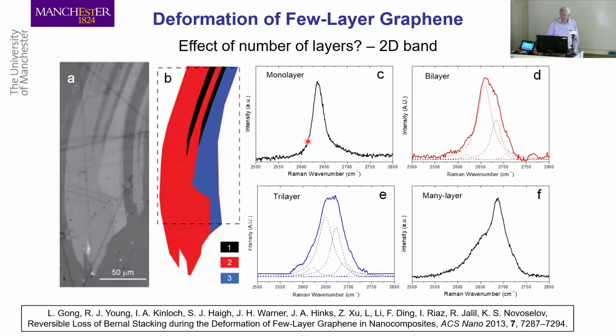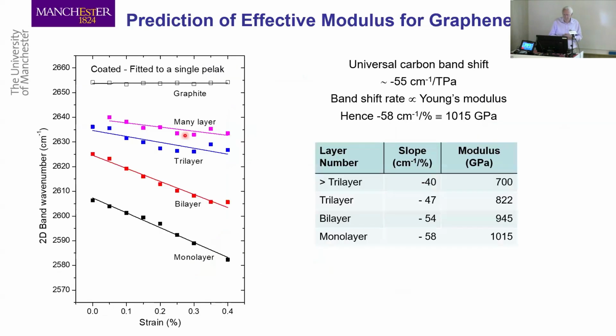And you can see from the Raman spectrum of the 2D band that you get quite different shape peaks. This is because the electronic structure of the material is different with different numbers of layers down at this level. So that's quite interesting. But what we found was that when we looked in detail at these bands, funny things happened when you deform the material and measure the peak position as a function of strain.